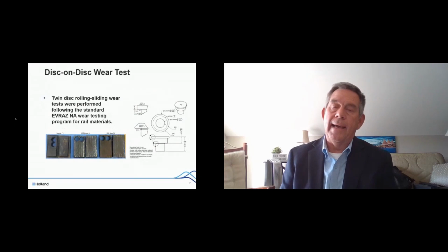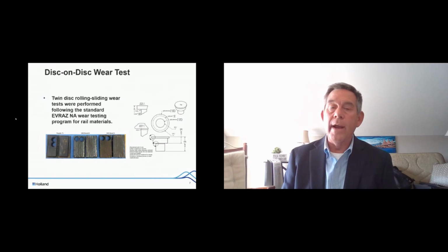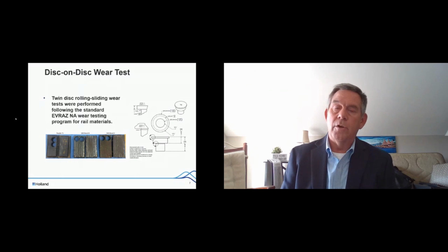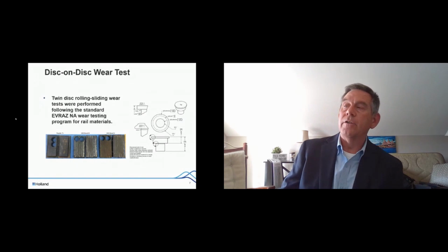The next was to look at how well this material wears in this application as a train is passing over it. And for that, we utilized what's called a disc-on-disc wear test. We literally cut out discs of the material after welding, and then rotate the discs as they press against each other, applying a pressure. One disc is rotating, the other disc is resisting the rotation, and then you measure how much material wears off the disc based on the number of cycles.